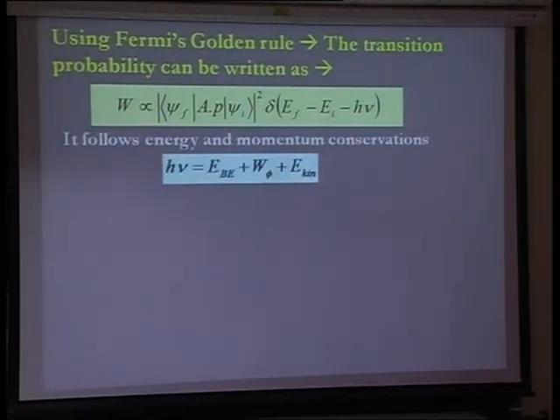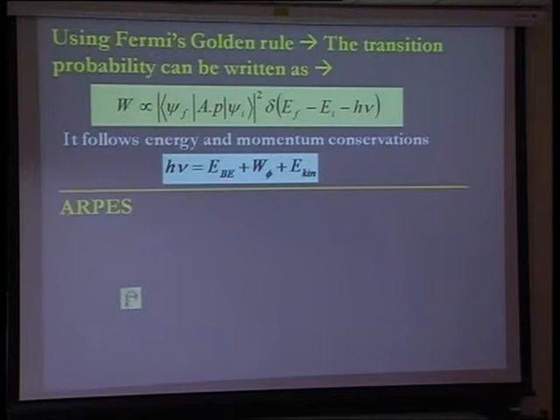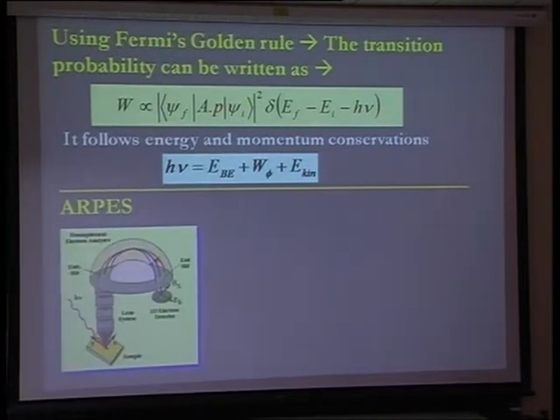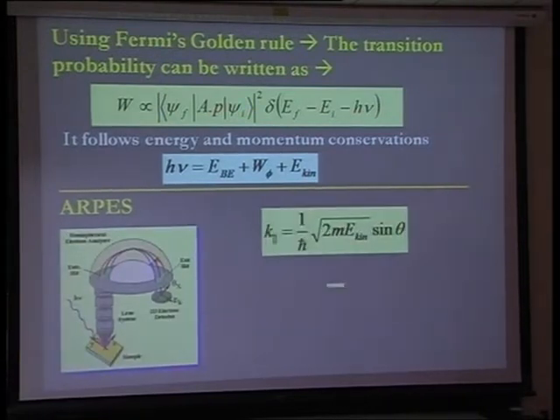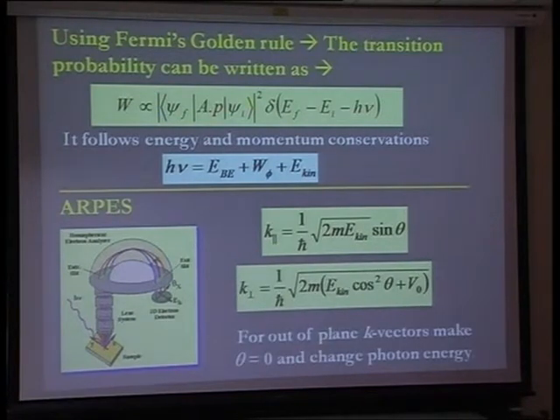And the energy conservation and momentum conservation allows you to actually find out the energy and momentum of this photoelectron that comes out. So what you do experimentally, if an electron comes out at a certain angle from the sample, due to this lens and various electronics used in this technique, you can exactly determine at which angle they are coming out. Because this red one can be mapped onto a certain location of your detector. So depending on that, you can measure the angle.